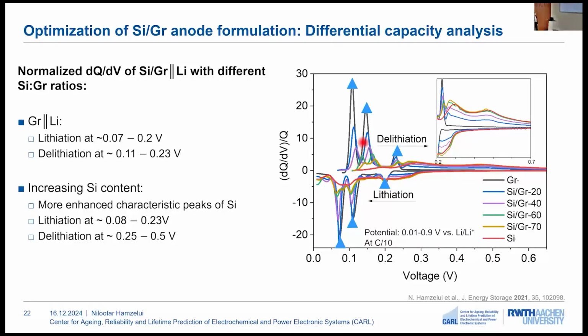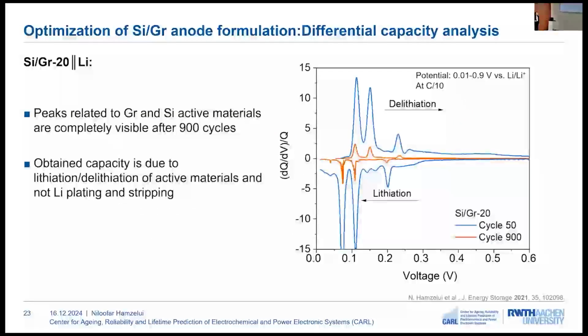On the other hand, with increasing silicon content, the intensity of the specific peak for silicon is increasing. Then the electrode with 20 weight% silicon was also measured after 900 cycles. And here we can clearly see the peaks which are related to silicon and graphite. This indicates that after 900 cycles, we are seeing the capacity in this electrode because of the participation of the graphite and silicon active material, and it is not due to lithium plating or stripping.